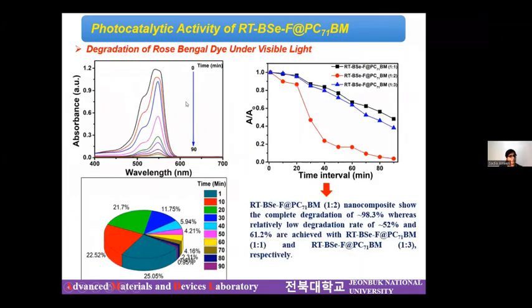At first, we didn't incorporate the photocatalyst into the experiment, just to see the effect. And here we found that nothing happened, the degradation did not occur. However, soon after incorporating the photocatalytic material, the degradation suddenly started. That means our nanomaterial is promising for the photocatalytic degradation of Rose Bengal dye. And we did it through the UV absorption method.